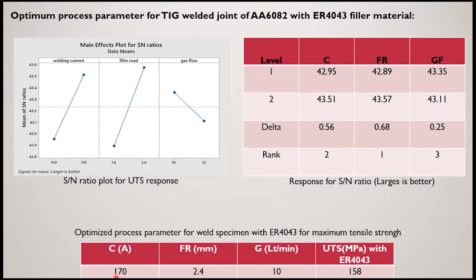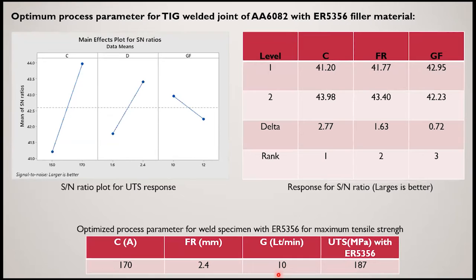Here we can see the maximum tensile strength of the weld specimen with ER4043. We are getting the current level at 170 ampere, the filler rod level at 2.4 mm, and the gas flow rate level at 10 millimeter. And we are getting a maximum ultimate tensile strength for the weld specimen with filler wire 4043 of 158 megapascal. This is the optimization of process parameters for the weld specimen with filler wire 5356. Here we have performed the same thing. Here we are getting the optimized process parameters: current at 170 ampere, filler rod at 2.4 mm, and gas flow rate at 10 mm.